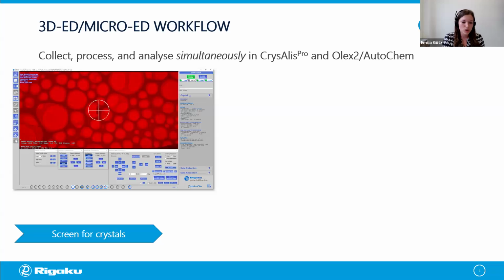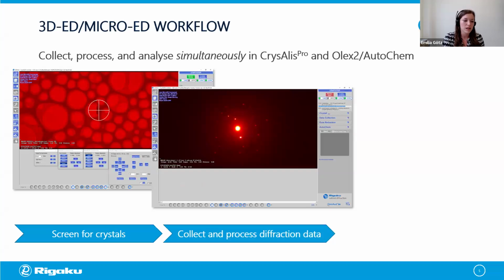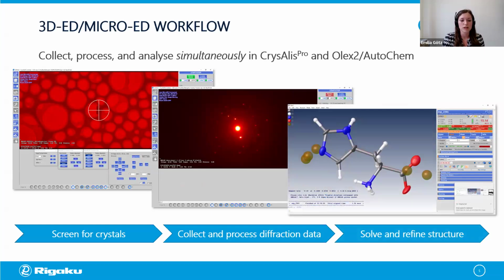The instrument control, data collection, and finalization are all done in CrysAlisPro. And after inserting the sample, you first screen for suitable crystals. And when you have found a well-diffracting one, you center it and collect the data. And concurrently, CrysAlisPro will process the diffraction data, and OLEX or AutoChem will solve and refine the structure, similar to our X-ray diffractometers. So let's have a look now at how this is done in practice.